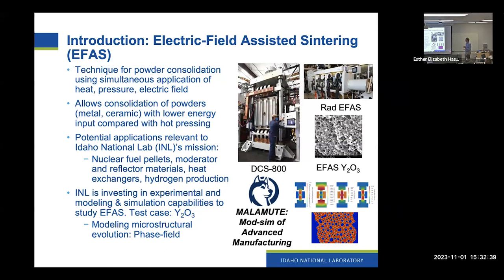As we do that, we can consolidate powders, both metal and ceramic, with quite a lot lower energy input compared with traditional sintering, or even compared with hot pressing, where you apply pressure and temperature at the same time. This could be applied to nuclear fuel, but I think it's also quite a bit broader. UO2 fuel is made by the traditional sintering process, and they have to hold it for very long times at high temperatures to get the porosity of these UO2 pellets down to low enough values that they can be used in the fuel rodlets. So certainly that's one potential application, but we have many other applications in mind.